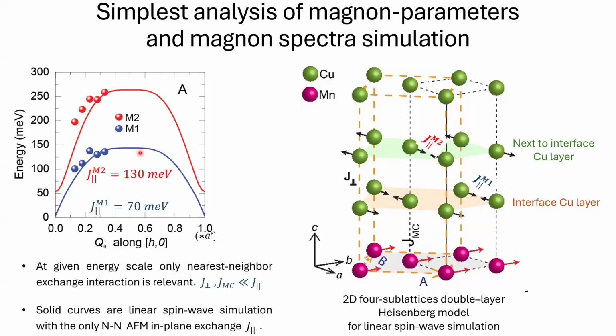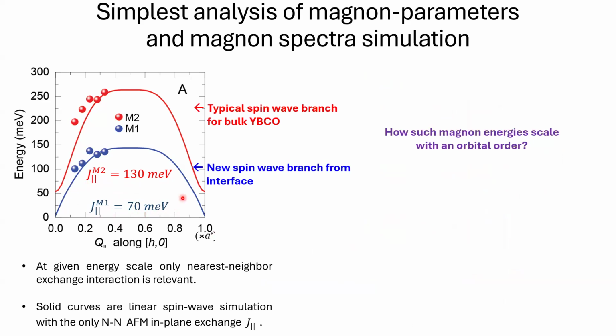For the bulk-like magnon, we have an exchange interaction which is typical for YBCO, the bulk magnon, which is very well known from previous investigations. And for the magnon seen at low energy, we should use another value, which is almost 2 times lower than the exchange interaction in the bulk. So how does such magnon energy scale with orbital order? This is again the typical spin wave branch in the bulk and the new spin wave branch from the interface.